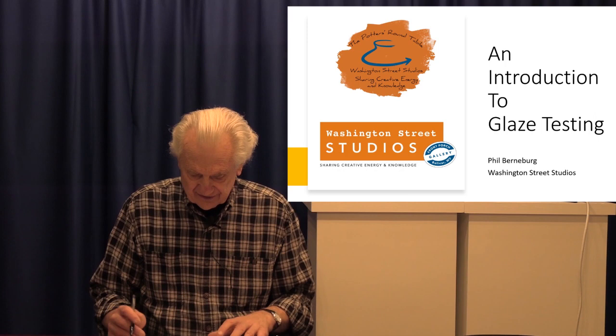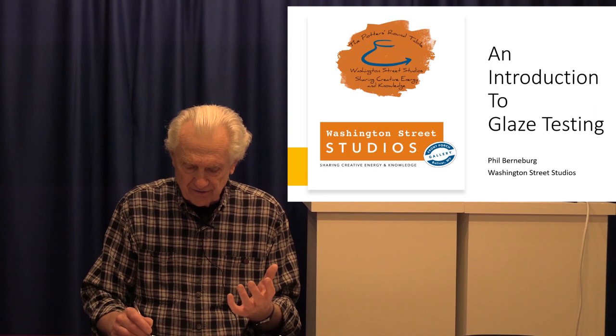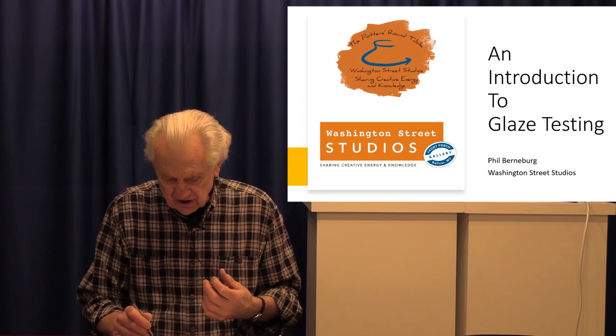And so I wanted to talk a little bit, just to summarize before we look at them, why I selected these particular examples. The EPK, when we added the extra EPK to the formula, it completely matted out the sample. So what I wanted to see was, by adding even a really strong colorant, how much would that colorant be affected by the fact that the glaze was made now completely opaque and completely matted out? How would it change the behavior of this colorant that we normally know is a fairly strong colorant? And as I mentioned with the 3124, because the glaze is fairly fluid, I figured it could accept a fair amount of zircopax without changing it. That was the reason. So I thought that would be a good one to try.